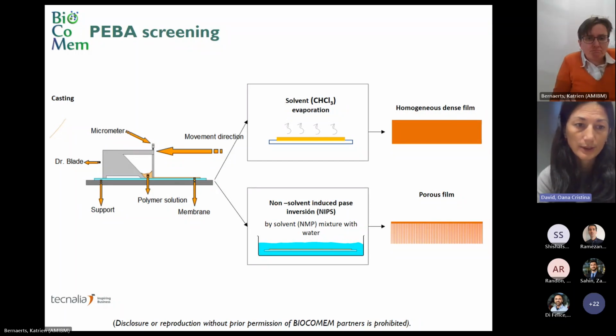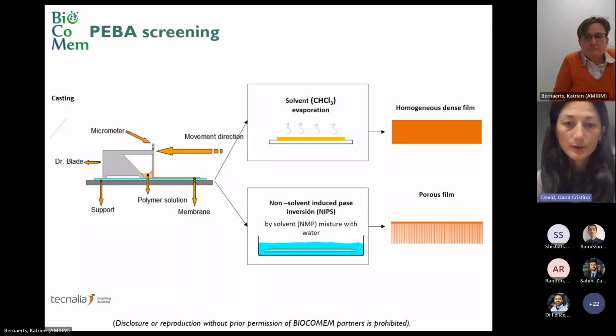In both cases, we had to start with a polymeric solution that was cast on a support using a doctor blade, a casting knife, as in the image on the left. Then to make a homogeneous dense film, we simply evaporated the solvent, in this case chloroform. And if we wanted to check the ability to form a porous structure by non-solvent induced phase separation, we had to start with a different solution that had NMP, N-methylpyrrolidone, as a solvent. We submerged the wet film in a coagulation bath containing water, and then we got this porous film. So we made these two types of membranes, let's call them like that, to compare the results.